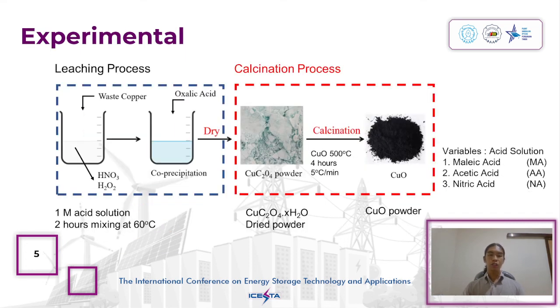The copper ions from leaching solution were recovered by adding 1 molar oxalic acid solution. After 2 hours of mixing at 60 degrees Celsius, light blue precipitates were formed and collected by gravity filtration. The cakes were washed and dried in a vacuum oven for 12 hours. The dried cakes of copper oxalate x hydrate were ground and calcined in a muffle furnace at 500 degrees Celsius for 4 hours at a ramp rate of 5 degrees Celsius per minute.